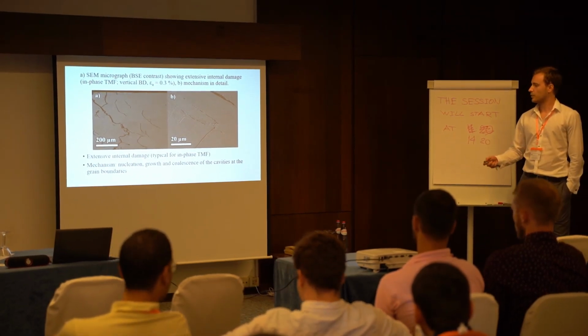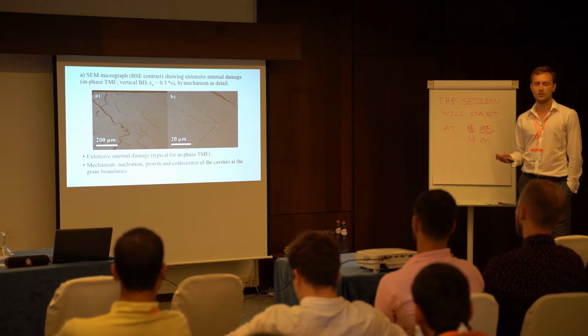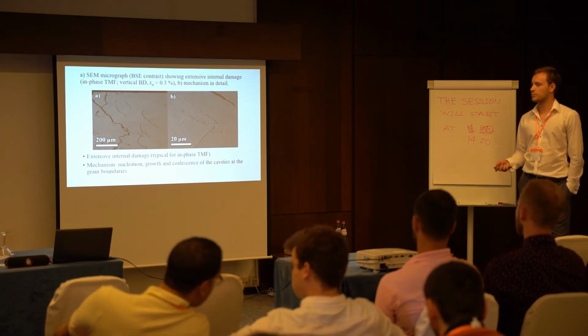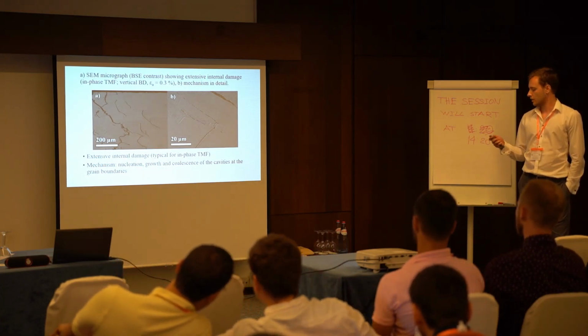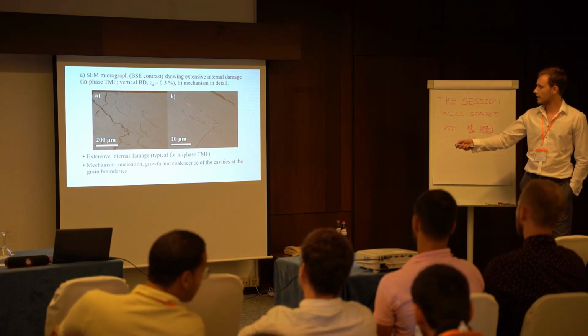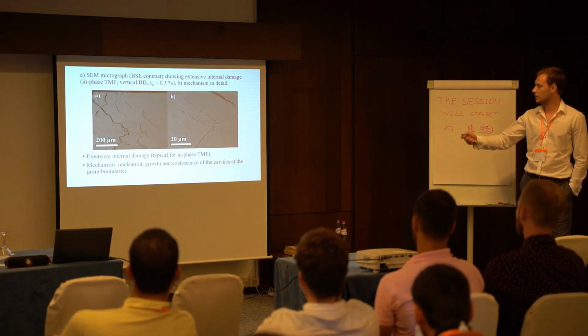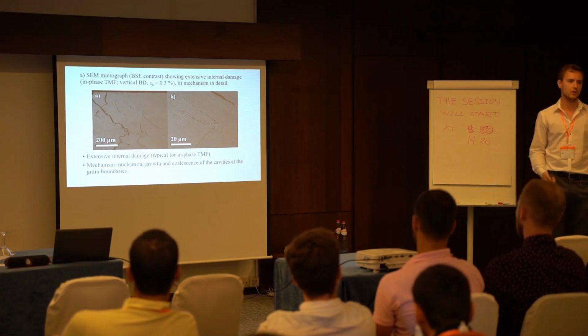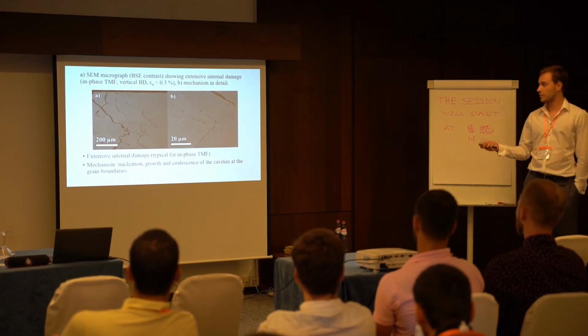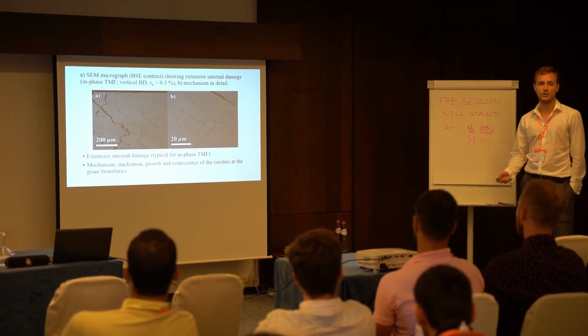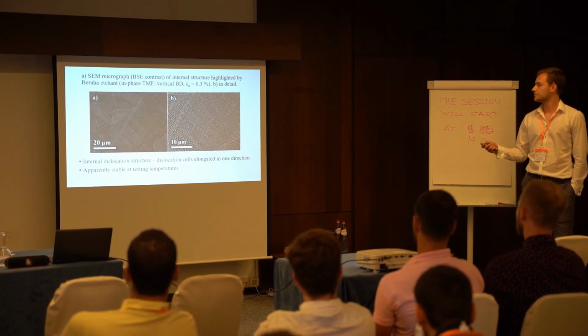Yeah, so there was extensive internal damage, and the mechanism was of creep origin. It's clearly seen in picture B, we had nucleation, growth, and coalescence of the cavities along grain boundaries. That was the primary damaging mechanism in in-phase tests in general.